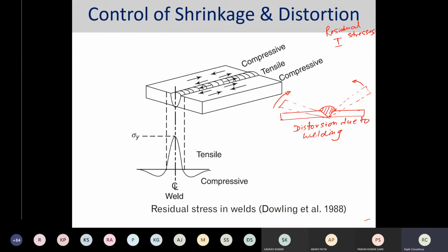There are a few other points to reduce the shrinkage forces. For example, you can utilize only a few passes to complete the weld. You can utilize proper edge preparation and fit up. You can utilize intermittent welds, and you can also allow the shrinkage to a certain extent.